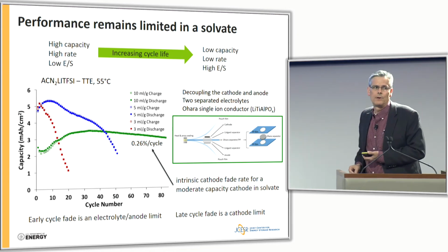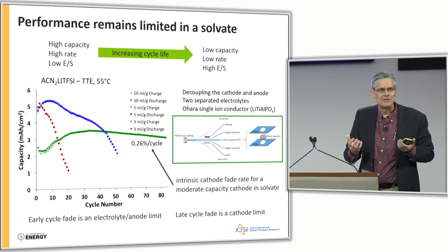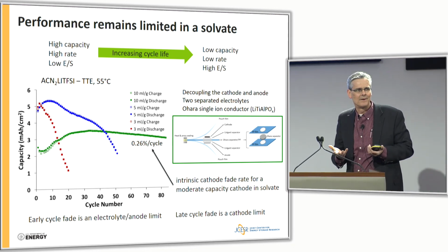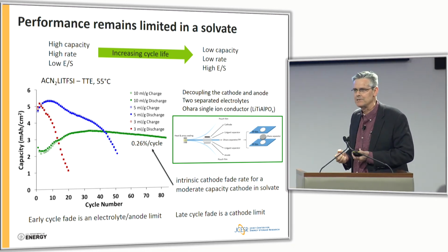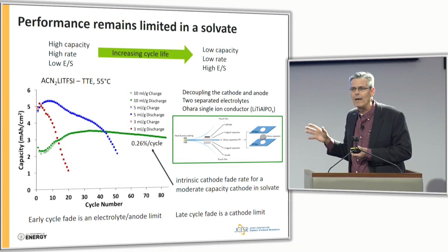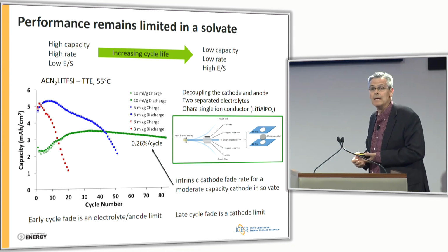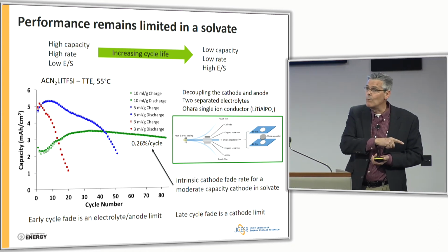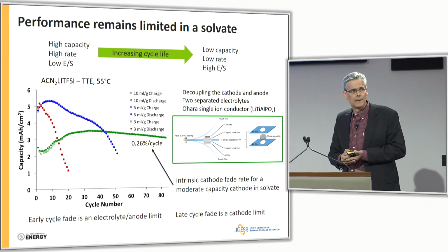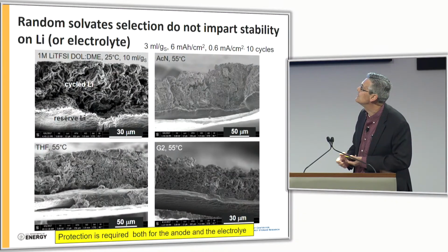Later stage failure really has to do with the same sort of issue that we've been grappling with here, and that is stranded lithium sulfide within the cathode structure itself, which means that for our reaction mechanism, our reaction pathway, we may need to augment the redox mediation activity through a designer molecule in much the same way that Brett showed you the electrolyte genome helps identify what we should be synthesizing with JCESR.